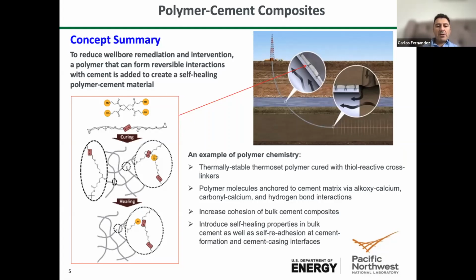So the idea is that the polymer, if it's homogeneously distributed in cement and can interact with different components of cement, in the presence of a fracture, due to concentration gradient and also pore pressure and capillary forces, can migrate to the fracture. It debonds nearby the fracture, migrates to the fracture, and then bonds back at the fracture, not only filling the fracture but also forming a chemical bond and restoring the mechanical integrity of the material. That's the concept, and it is now protected with 2 patents here in the United States, and we'll be looking at different chemistries. I'm going to show you a few examples in the next slides.